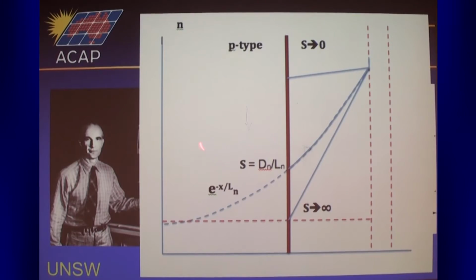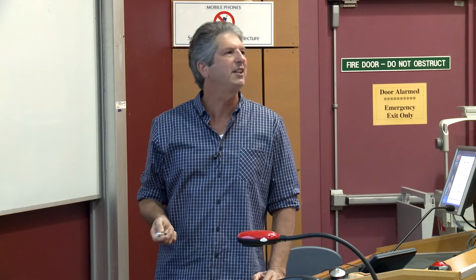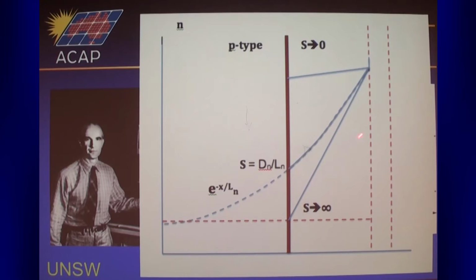If you have the value of the surface recombination velocity just right, and in this case it's equal to this diffusivity I mentioned divided by the diffusion length, that decay constant here. So if it has that particular value, you don't change anything. The carriers get to the surface and it just looks to them as if the material continued on indefinitely. So that's the critical value in deciding whether you get behavior like this or behavior like that.